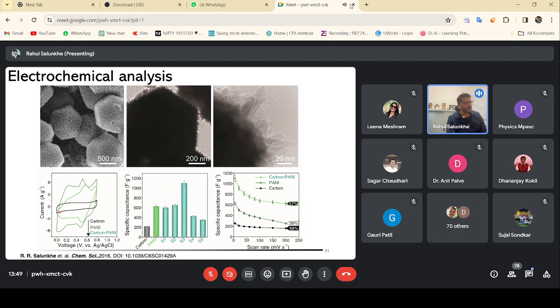Now we can clearly see this reflected in the electrochemical studies also. We can see a very rectangular CV shape in the case of carbon, whereas in the case of polyaniline, some redox peaks can be observed. Of course, polyaniline is a redox material, and because of that, certain redox peaks can be observed. Whereas if we use this carbon-coated polyaniline, we can get a very rectangular shape of the carbon backbone, as well as the redox peaks associated with the polyaniline.